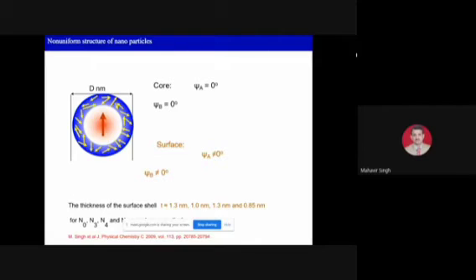Then we use the Mossbauer data for cation distribution. So we calculate the surface disorder thickness. And dear friends, there was fair agreement between the thickness observed through SQUID data and the thickness observed through Mossbauer. And I want to mention here that our group was the first with IUC people that calculated this surface disorder using Mossbauer spectroscopy, in coherence with the SQUID data.